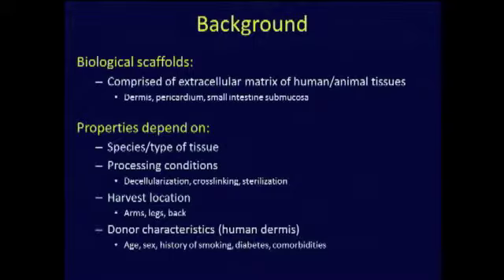The processing of these materials is proprietary to the companies, as these extracellular matrix undergo decellularization and sterilization, and that processing may have an effect on the actual graft integrity. Cross-linking is an intentional change to the graft to try to make the collagen more stable by intentionally adding bonds between the collagen matrix to decrease the amount of degradation of the material.